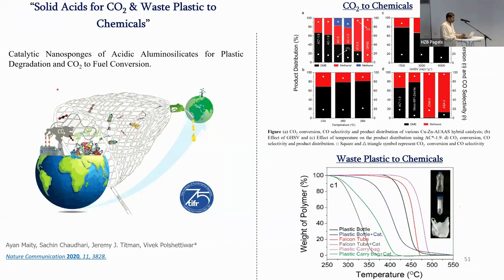This is another work where we showed that we can create solid acids. You know, most of the time solid acids are zeolites. They are extremely strong. But zeolite's problem is the microporosity, right? So not all the bigger molecules can diffuse in. So we asked this question, can we make a solid acid which has a strength like a zeolite, but is still accessible, so that a bigger molecule can diffuse in? And that's what we showed in this particular case.